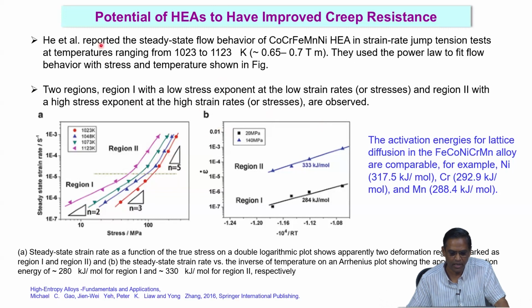He et al. reported the steady state flow behavior of the cobalt, chromium, iron, manganese, nickel high entropy alloy in strain rate jump tension tests at temperatures ranging from 1023 to 1123 K. They used the power law to fit flow behavior with the stress and temperature shown here. So what you see here is the steady state strain rate, that's the creep rate, versus stress, and then you have creep rate versus inverse of temperature, not homologous, it's an inverse of temperature plot.